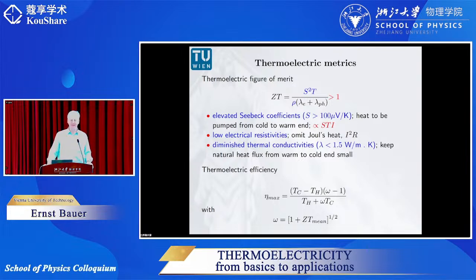Thermoelectric efficiency, ladies and gentlemen, is another feature. While the former one is a material-dependent property, the performance of a thermoelectric generator depends in addition, as you can see here, on the Carnot prefactor. So a thermoelectric generator is a thermodynamic machine. That means it is of importance to have a large difference between the hot side and the cold side. If this difference becomes small, then the efficiency of a thermoelectric generator becomes small as well. So the best would be to have on the hot side several hundred centigrade, and on the cold side just a couple of Kelvin.